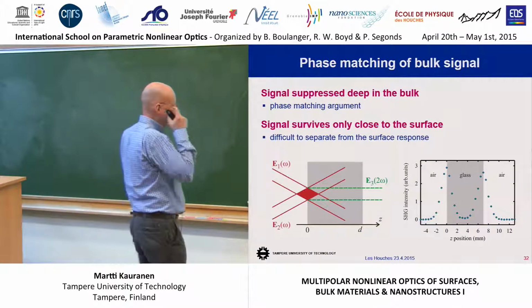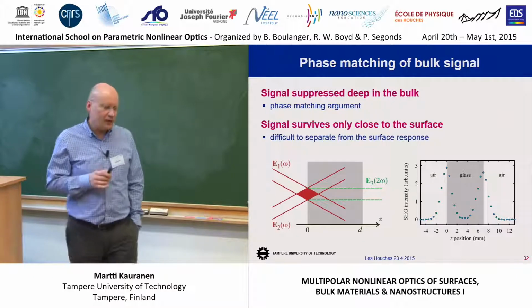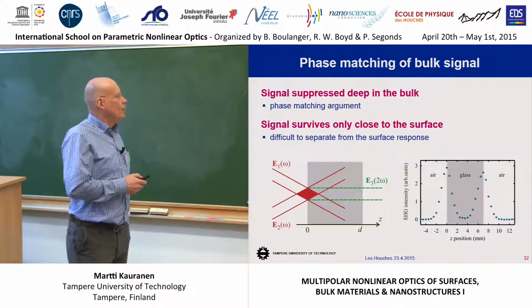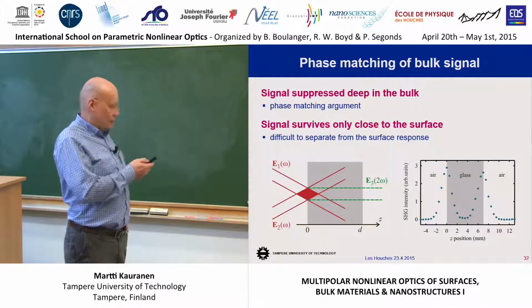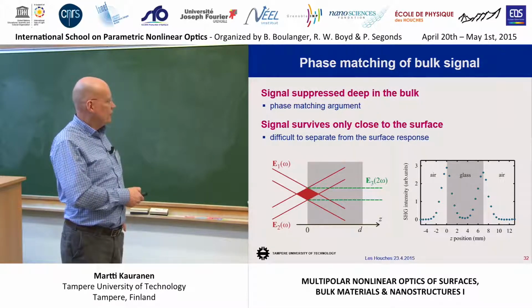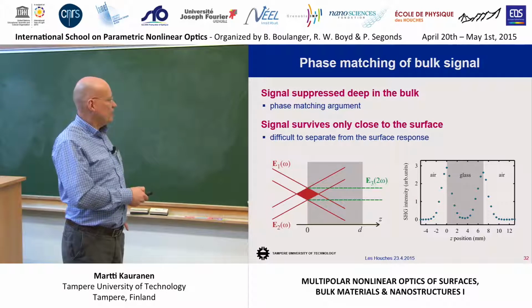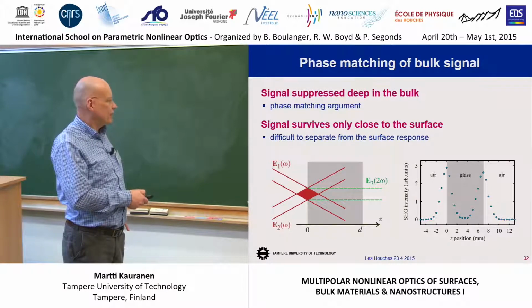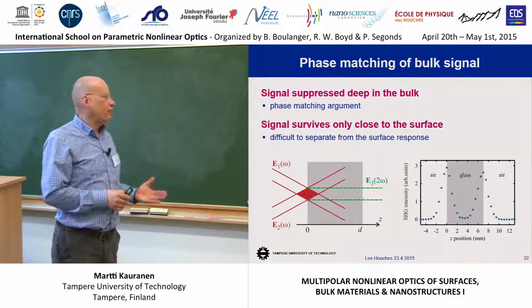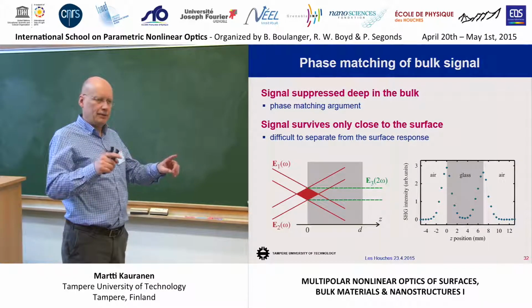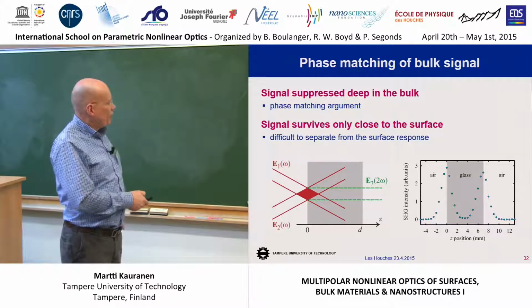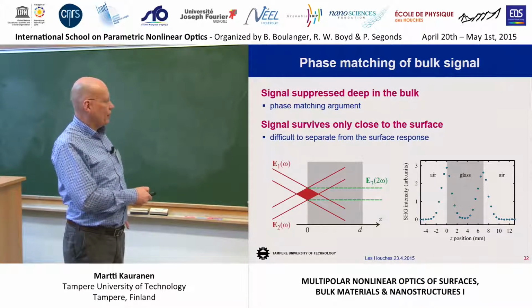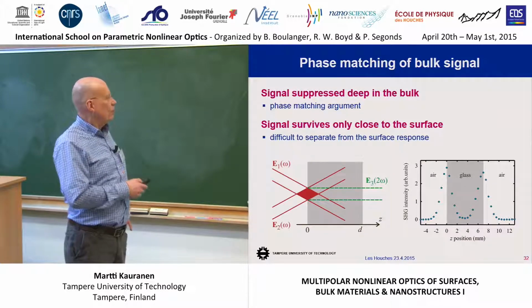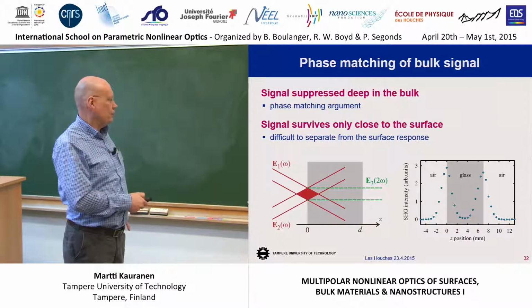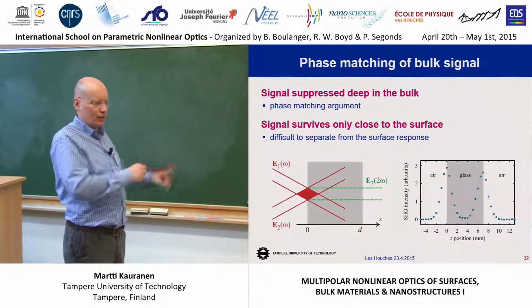But one more thing before we get into the actual experiment. There's a really interesting thing that's related to phase matching. So for the bulk signal, we have two beams that intersect within the medium, and then we create the second-harmonic signal in some direction. In a real experiment, we use finite beams, so beams with finite transverse size. Therefore, our interaction region is going to look something like this diamond here. And it turns out that there's a pretty strong phase mismatch because the beams cross each other and so on.